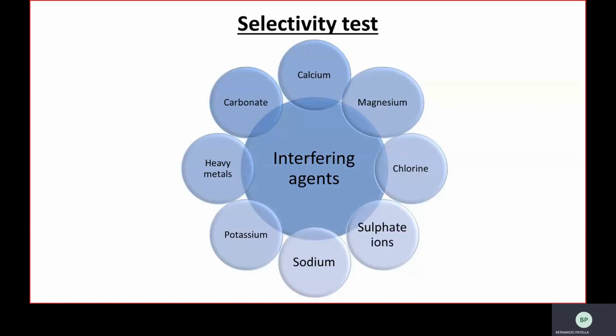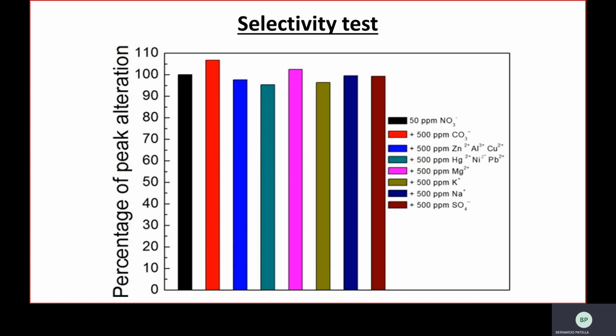Before testing the sensor with real samples, selectivity tests were carried out. Particularly, the interference from carbonate, zinc, aluminium, heavy metals, magnesium, potassium, sodium, and sulfate were studied. All these chemicals don't produce any particular interference as shown in these figures. Indeed, the peak intensity of 50 ppm of nitrate increases or decreases less than 7% when 500 ppm of all these interferences are put together into the solution. So there is almost a negligible effect of these chemicals.